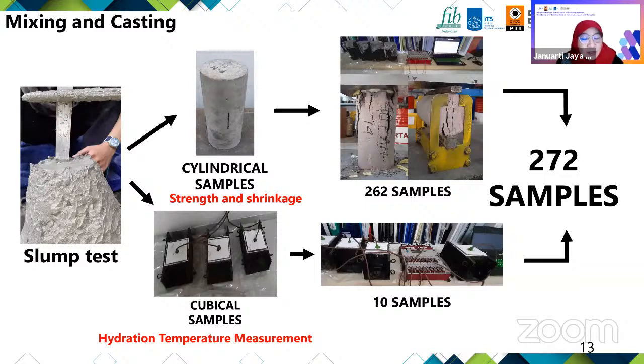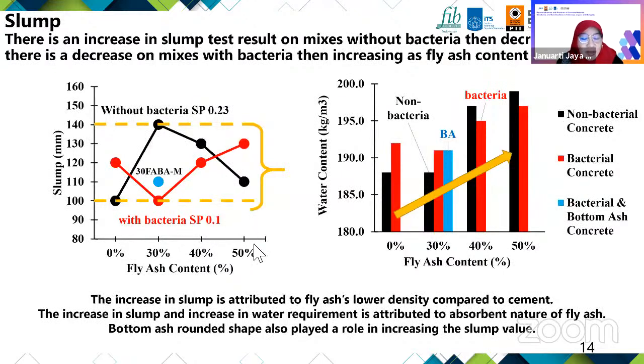The slump of concrete is something very important to analyze. As the ash content increases, in order to achieve good workability for the slump target of 10 to 14 centimeters, we add water in the mixture as the fly ash content increases. The ash indeed absorbs water during casting. As expected, bacteria increase the workability of the mixture. So we can see here, and the blue one here, the specimen containing 30% of bottom ash.